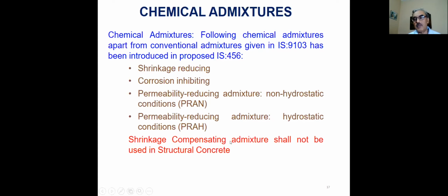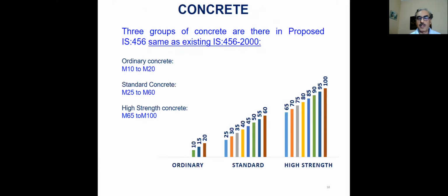Shrinkage compensating admixtures shall not be used in the country. This we are not permitting. Shrinkage compensating admixtures are those which cause expansion to some extent to cover up the shrinkage, so they are not reducing the shrinkage, they are doing some expansion. If expansion is little more than the shrinkage, it can be disastrous. So this is not permitted in structural concrete.